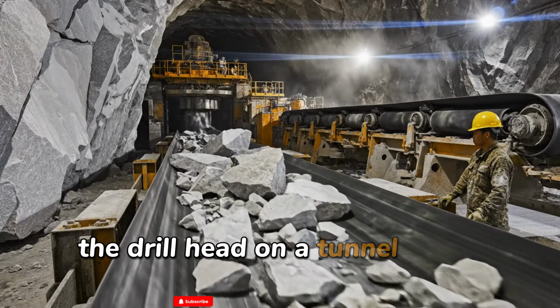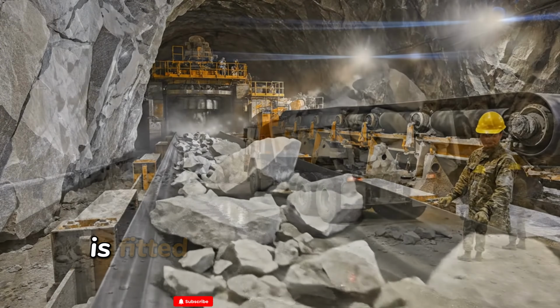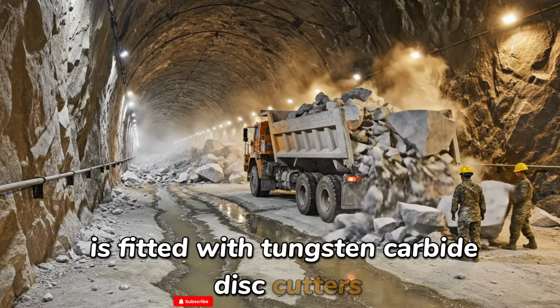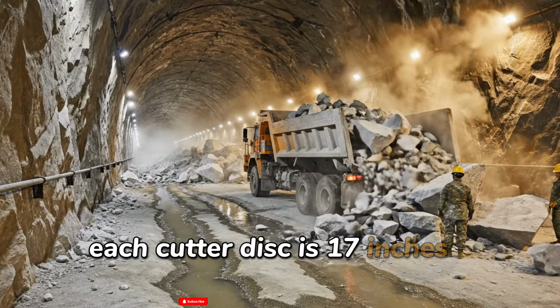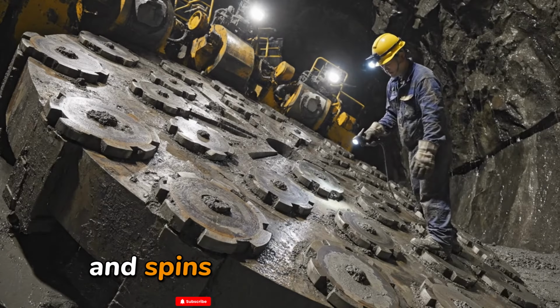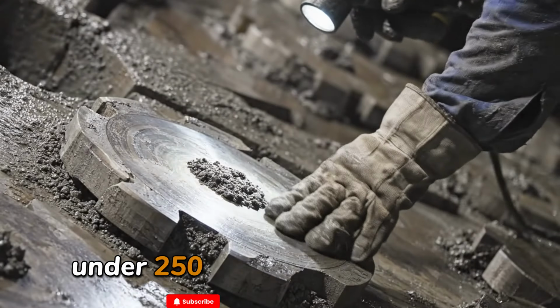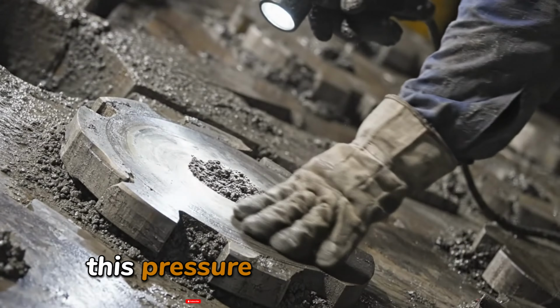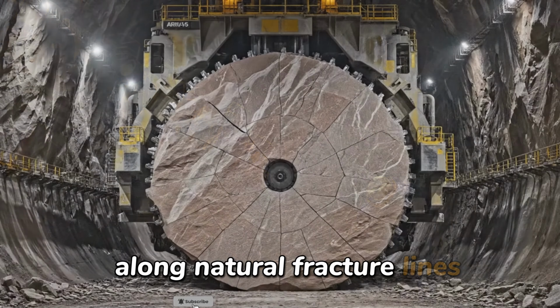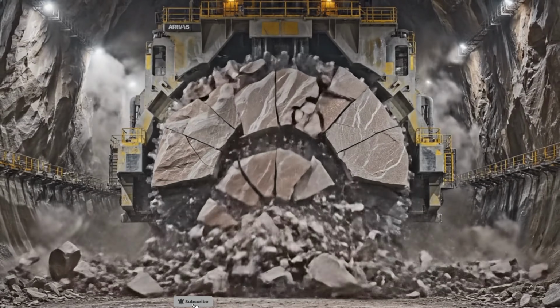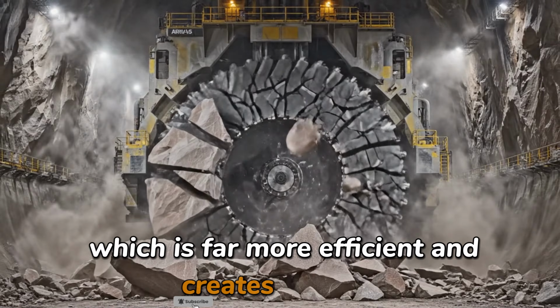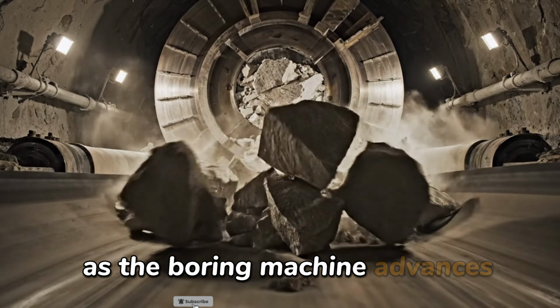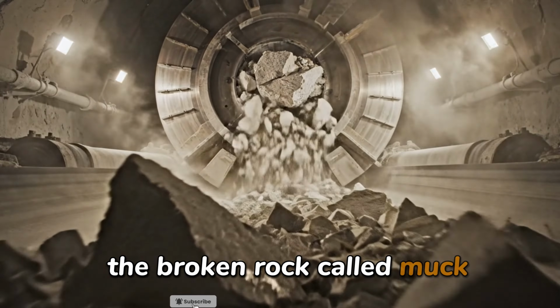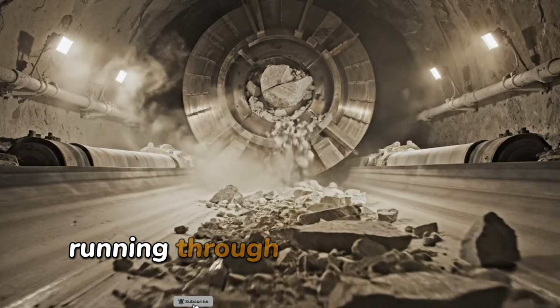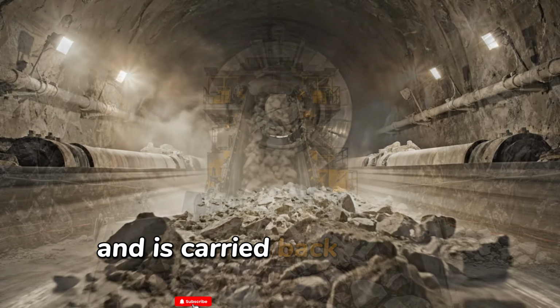The drill head on a tunnel boring machine used for granite rock is fitted with tungsten carbide disc cutters. Each cutter disc is 17 inches in diameter and spins against the rock face under 250 tons of thrust pressure. This pressure cracks the granite along natural fracture lines rather than grinding it down, which is far more efficient and creates less heat. As the boring machine advances, the broken rock, called muck, falls onto a conveyor belt running through the center of the machine and is carried back out of the tunnel.